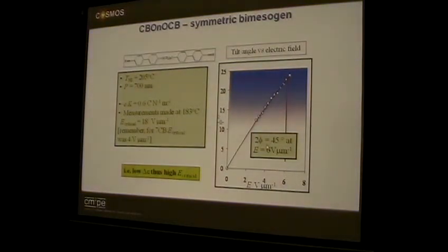So for a device, in principle, a tilt angle or a combined switching angle of 45 degrees, 6 volts per micron, would give you a perfect device between cross polarizers. If you take a piece of stretched plastic, rotate it between cross polarizer and analyzer, you see a maximum signal at 45 degrees. The optic axis is 45 degrees to the analyzer.